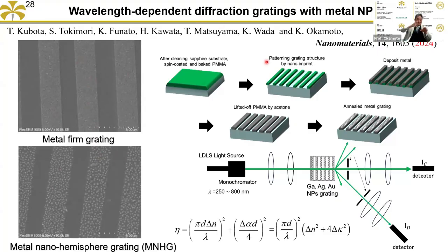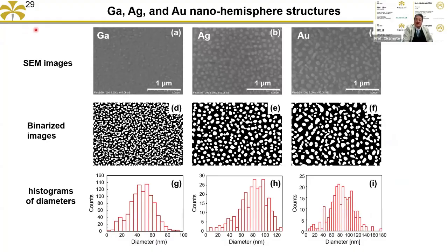Okay. And also we fabricate the metal nanoparticle grating structure to obtain a wavelength dependent diffraction grating. So usually a diffraction grating is not wavelength dependent, but if you fabricate the structure, so we use gallium and silver and gold for each wavelength region. And the property of the metal is different, and in the gallium case the size is a little small. That's a histogram, diameter is 50 nanometer, and another one is almost 100 nanometer. But we fabricate that for the grating structure.